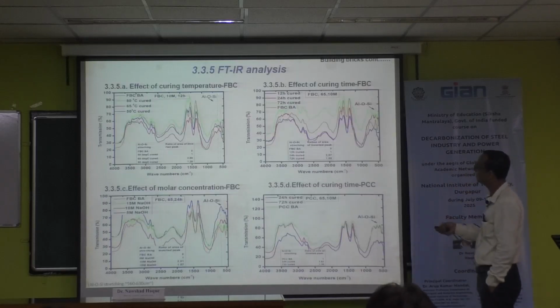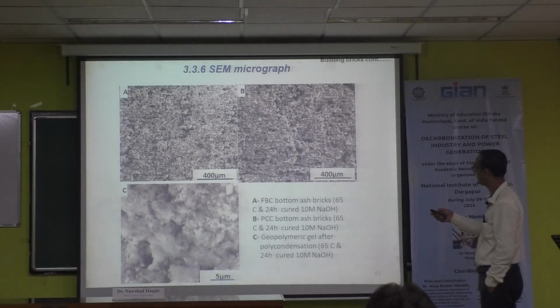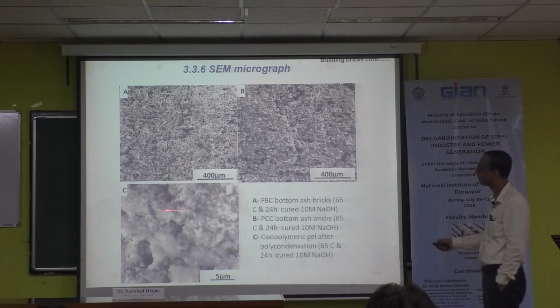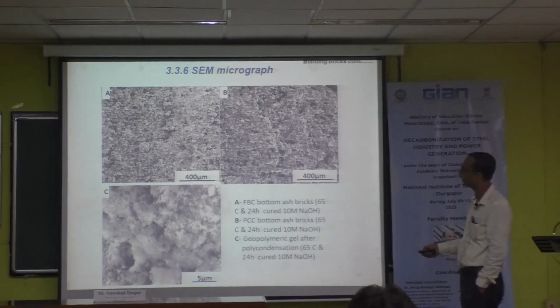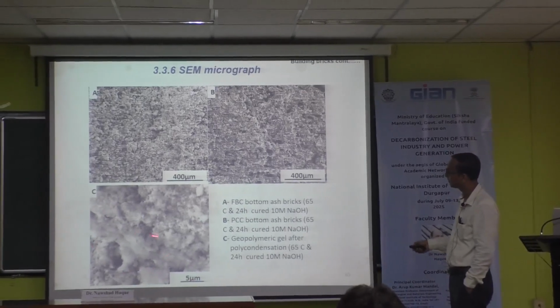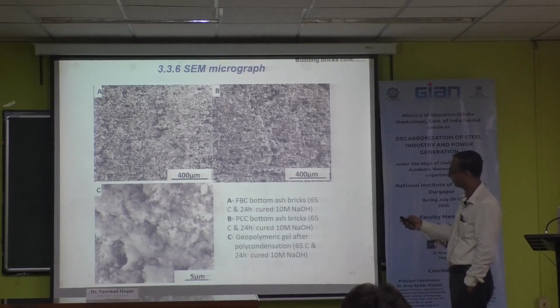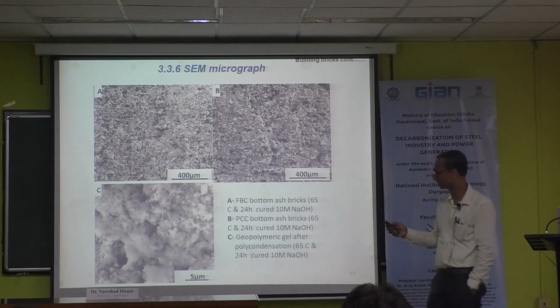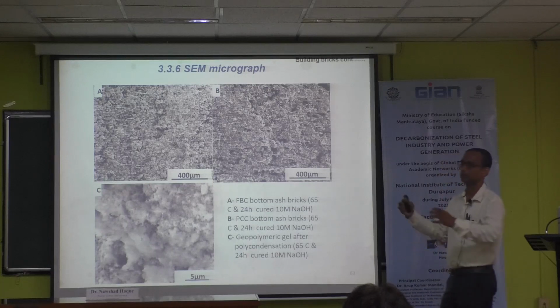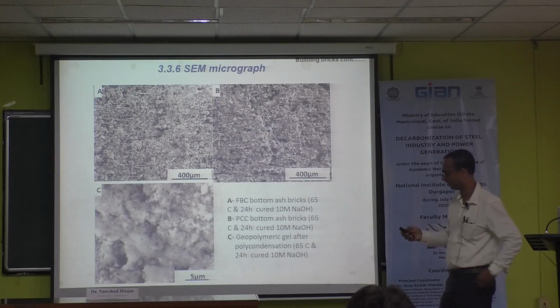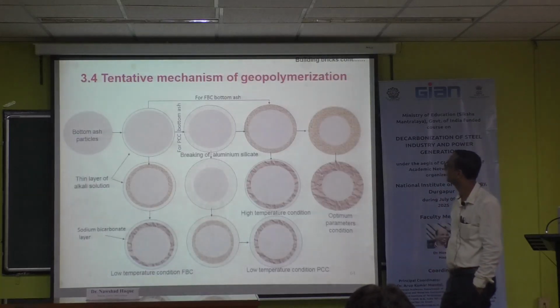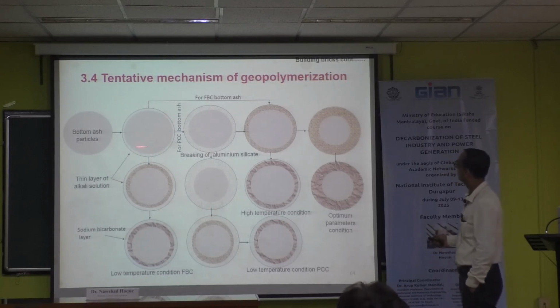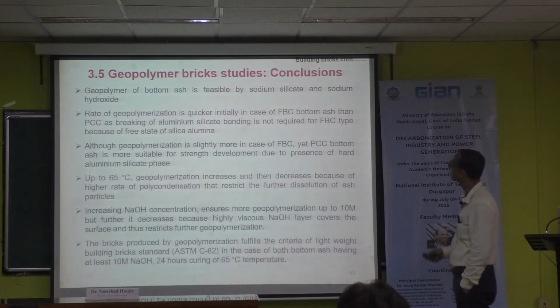This is the SEM analysis to see the morphology. This is the same image after geopolymerization. This white is actually the geopolymer formation. Okay. When you see under the microscope, you can see this type of white edges are there. If you do the EDX analysis, then you can see that an alumina silica network is formed. Then this is actually the mechanism of how this geopolymer is formed. Then this is the conclusion.